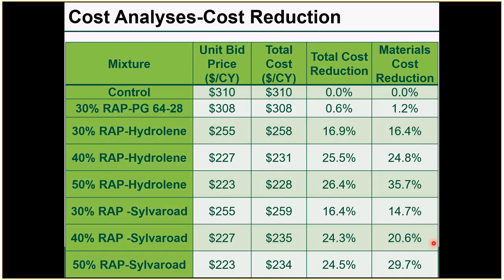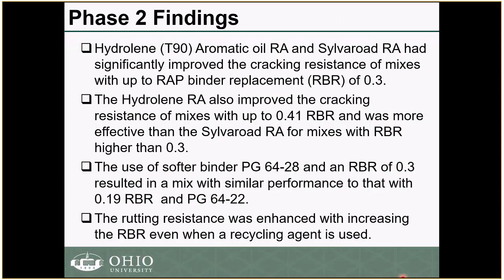Again, you can see that once you go to the 50, you can start seeing a much higher cost reduction in terms of the materials. But again, at those percentages, as contractors, I think there are other things that the contractor might have considered that resulted in basically increasing the cost as compared to only the cost of the material. But in general, you can see a significant cost reduction, even when using a recycling agent, and that depended on the percentage of RAP.